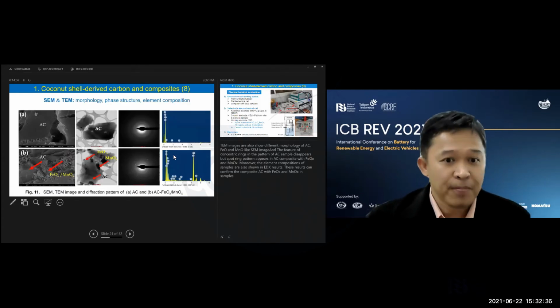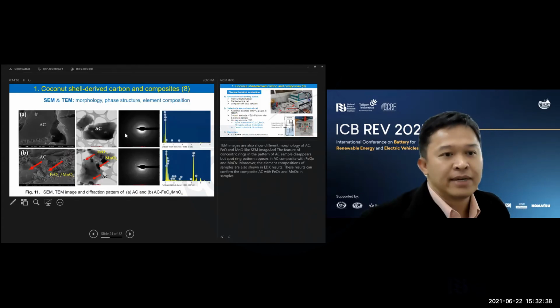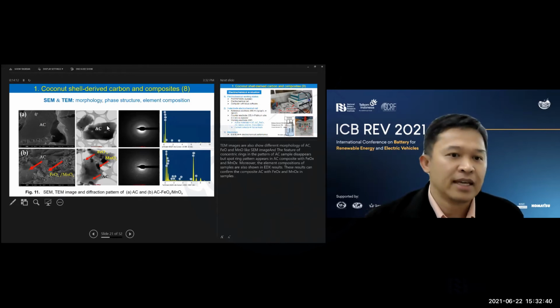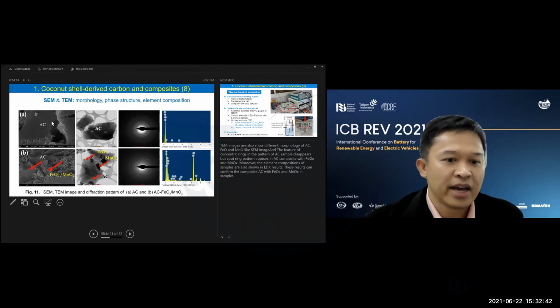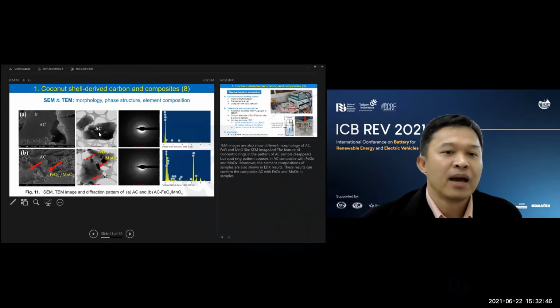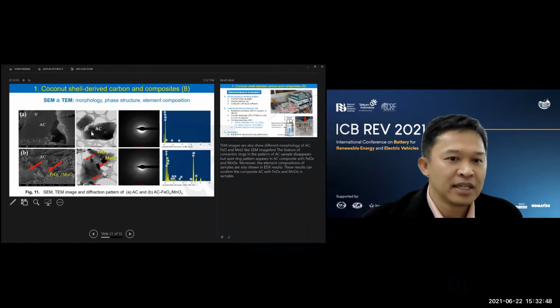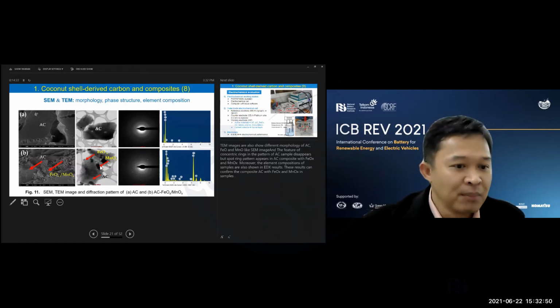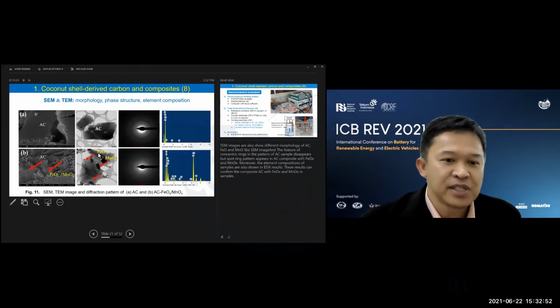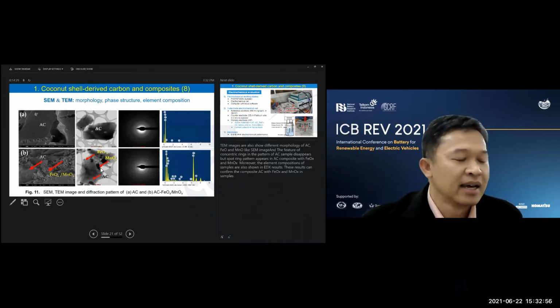In TEM, we can see the formation of the composite clearly. For example, in figure 11A, we can see the activated carbon. This is the pure one, and for the composite, we can observe the formation of iron oxide and also the manganese oxide, and this can be confirmed by the EDX technique.